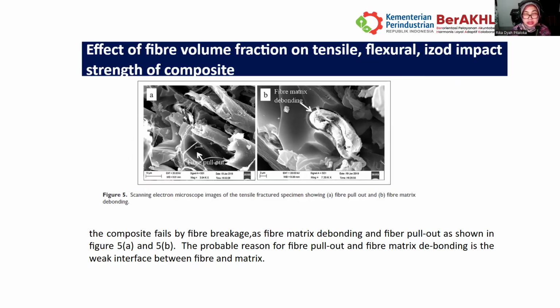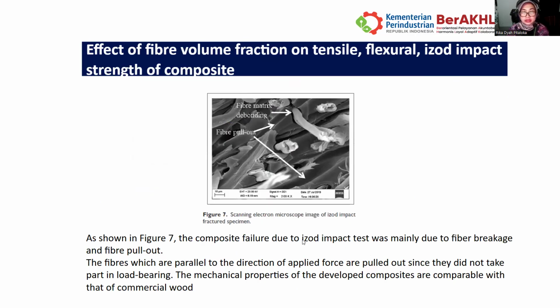The probable reason for the fiber pull out and the fiber matrix debonding is the weak interface between the fiber and the matrix. This one is figure 7, the scanning electron microscope image of the izod impact fracture specimen. As shown in figure 7, the composite failure due to izod impact was mainly due to fiber breakage and fiber pull out. The fibers which are parallel to the direction of the applied force are pulled out since they didn't take any part in load bearing.